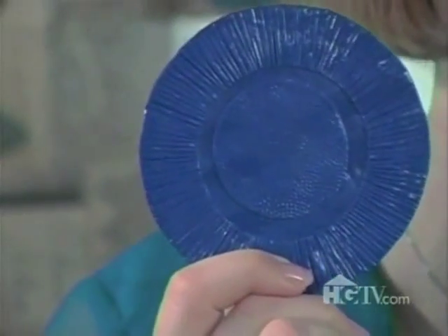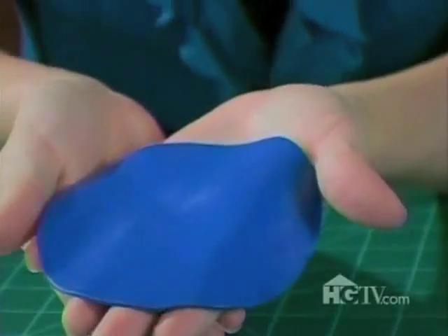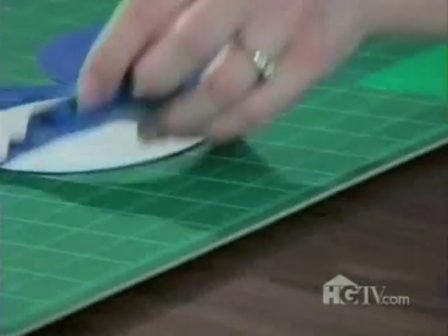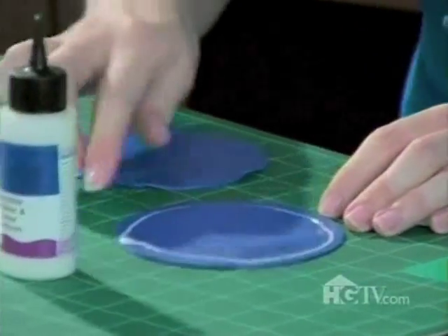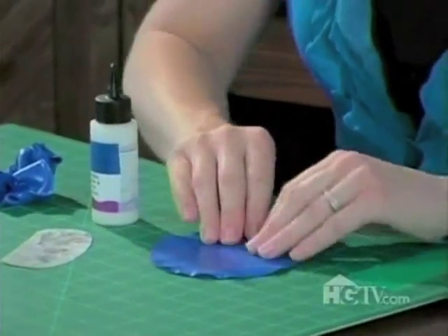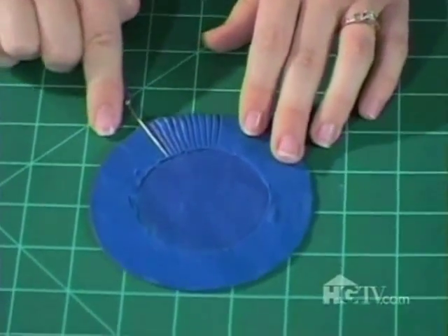I'm back and now I'm going to make my poker chip coaster. To get started, I'm going to take my polymer clay and roll it through the pasta machine. My clay is rolled out. Now I'm going to use the template I've already cut out and cut around it with my needle tool. Now that this is cut out, I'm going to bake it in my toaster oven for 30 minutes at 275 degrees. The bottom is baked. Now I'm going to do the same thing to make the top piece. I'm going to use liquid polymer clay to attach this piece to the baked piece, just around the edge, because I'm going to take out the center area. I'm going to take a smaller circle template to cut out the middle, because that's where the drink goes. I'm going to use my scraper to take out the center and set that aside for later. I'm going to use my needle tool to make impressions around the outside to make it look like a poker chip.